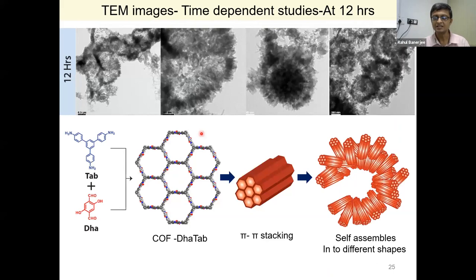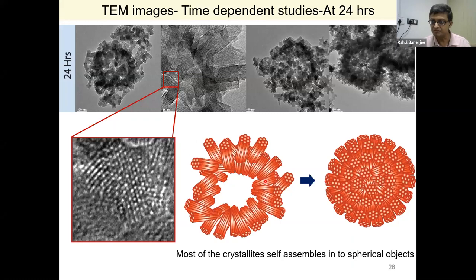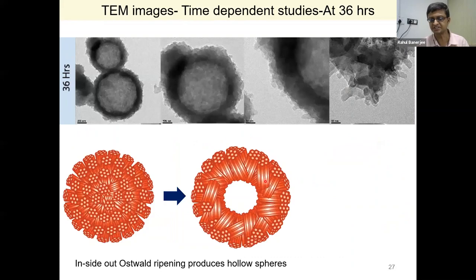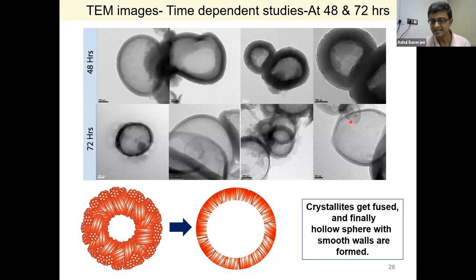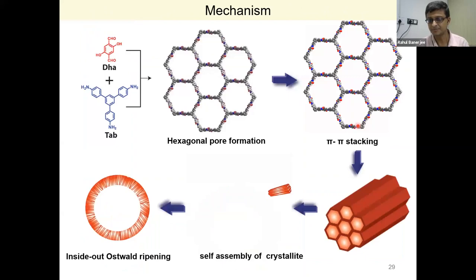The mechanistic analysis showed that these crystallites form nice nanoparticles, which assemble together into a haphazard network. These networks then fuse among themselves — like Ostwald ripening — eventually forming a nice hollow spherical structure. These hollow spherical structures are extremely porous, exactly like the nanoparticles when first synthesized, with very little change in crystallinity. In all cases, the particles don't change their internal structure, but overall they give a very nice morphological modulation from starting point to finish.